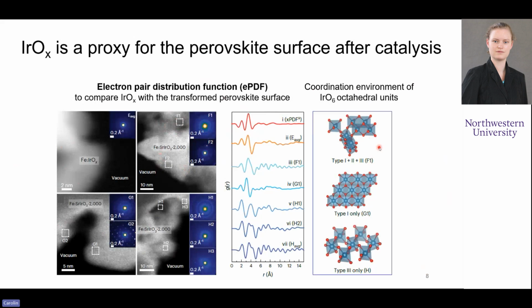There are also regions in the perovskite that show only the type 1 face-sharing octahedra, as well as there are regions that only show corner-sharing octahedra. So the structure in the perovskite surface is a little bit more heterogeneous than what we've seen in our base iridium oxide material, but still the same kind of structural motifs are present in both surfaces, which means we get to use our paracrystalline iridium oxide as a proxy for this perovskite surface.